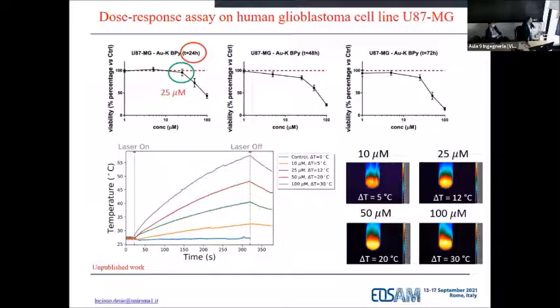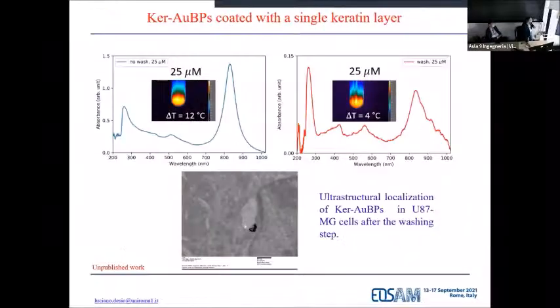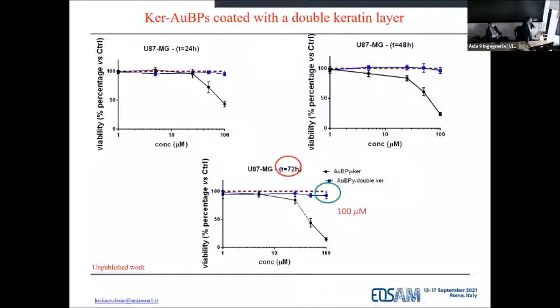So then we said, okay, we are not really happy. What if we try to increase the coating of this layer? So then we went through a double functionalization. This is just to give you an idea about the single layer, of course. Once you wash the particles, we have very few particles in the cell, and the temperature increases 4 degrees C. So then we said, what if we try to double the layer, to make it thicker?